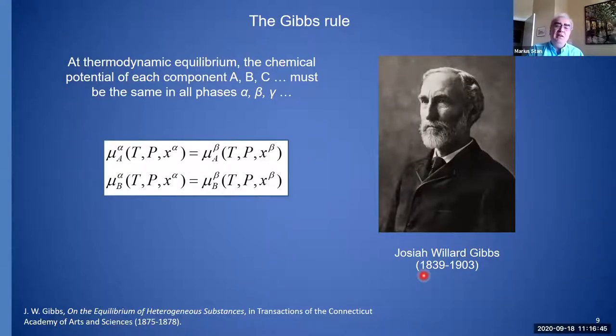Lucky us, we got an opportunity to calculate equilibrium between various phases thanks to Gibbs, an American scientist who lived his life in heaven - he was born and died in New Haven, Connecticut. He realized that minimizing the free energy of the entire system is the actual target for any equilibrium calculation. It is not the phase that has the lowest free energy, it could be a mixture of phases. He formulated that in terms of chemical potential. Equilibrium is attained when different components have the same chemical potential in the phases that are at equilibrium.